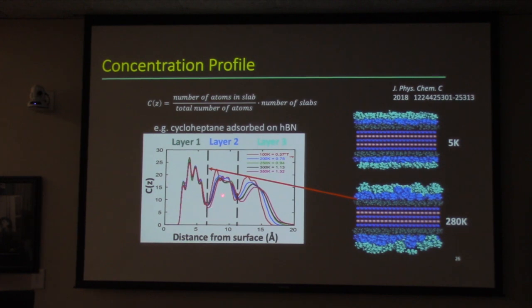And you'll notice that there's a bunch of temperatures that we've done these studies at, and as the temperature goes up, they get more and more distributed. That's partially because the surface is starting to lose hold on those particular molecules. What's rather interesting is that we found that you can have layered liquids. The molecules closest to the surface stay pretty well organized. Then the next layer, depending on the temperature, starts to translate, and then the one above that. But they tend to stay within their particular layers, although you'll see there's a little bit of interlayer traffic here.